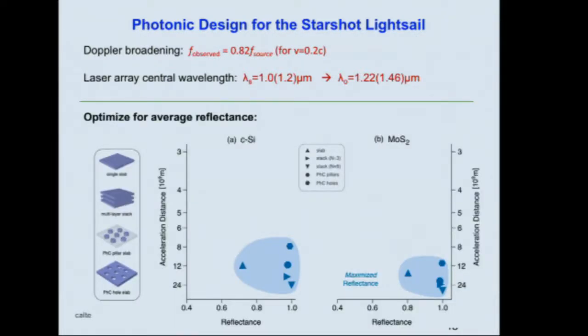And here's what we found. We found an array of solutions where the reflectance was close to 100%. And the good news is that for the two candidate materials we analyzed in detail, multi-layer molybdenum disulfide, like the materials I showed you we made solar cells of on Tuesday, or thin films of crystalline silicon, there are many solutions. I have photonic crystals, I have slabs, I have stacks of materials that all work.